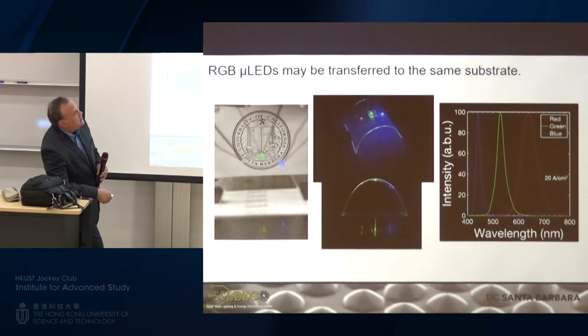So if you have a 10 micron by 10 micron chip, that's your LED, what is the active area of the light emissions? In the ones with the thing, it's roughly 1/4 of that. And why do you need to have hundreds of amps per square centimeter of light current to go through that? For the display, that would burn it out. Because with OLED, we use milliamps per square centimeter. But we use up the whole area.